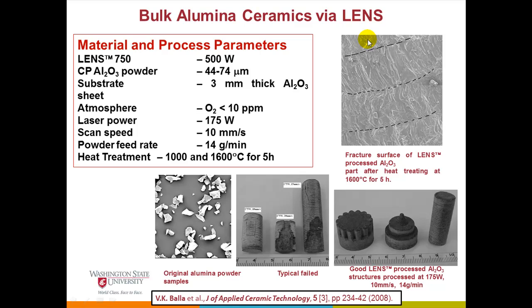What's unique here, and I don't think anybody has done it before, is we are seeing a columnar grain structure, which is very typical of cast metallurgy, cast metal structure. But we're getting that columnar structure in ceramics because we're melt casting ceramic. We don't normally melt cast ceramics - we take the ceramic powder, sinter it, and so on. Here we're actually melting the ceramic powder, casting it, and building parts.